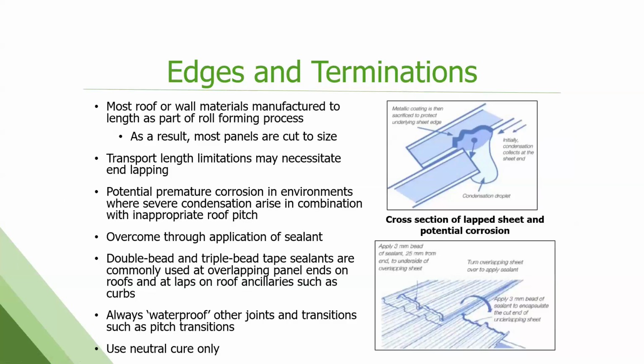Edges and terminations. Most roof and wall panels can be made to the exact length they need to be, right? We want to minimize field cutting as much as possible. However, we know that there's transport length limitations. You may have to end-lap depending on the length of panels and what the design of the building looks like. So you want to make sure you do those laps in the right direction, right? So water can't get in between. Use a sealant. Double bead or triple bead tape sealants are common at overlap panel ends and work well. You want to make sure you waterproof any of the joints and transitions.